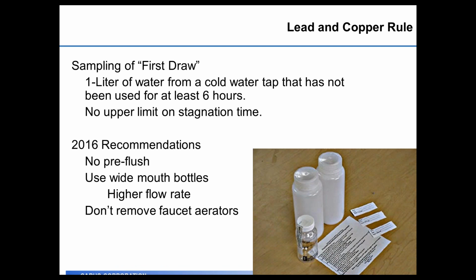The lead and copper rule is different than most regulations because it requires a sampling of a first draw. So this means the sample is collected at the consumer's home, and it should be 1 liter of water from a cold water tap that has not been used for at least 6 hours in the consumer's home. The current regulation sets no upper limit on stagnation time. Technically, most water plants will tell their consumers they'd love that tap sample to be picked between 6 and 12 hours that it's sat stagnant, but there is technically no upper limit on it.